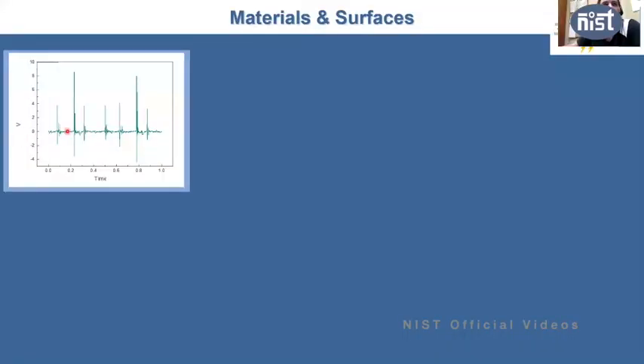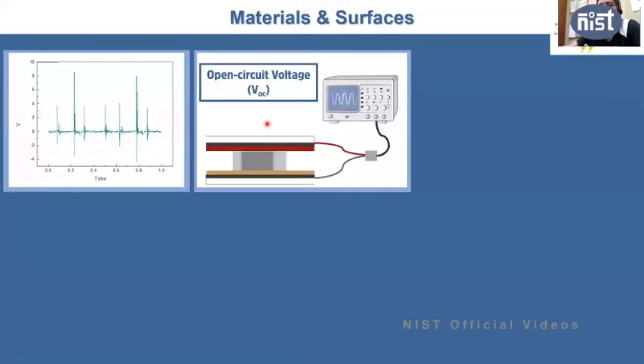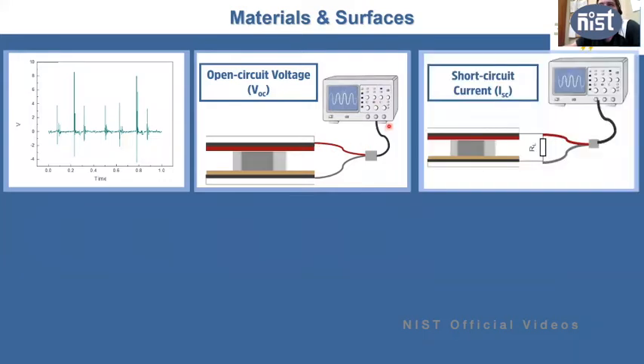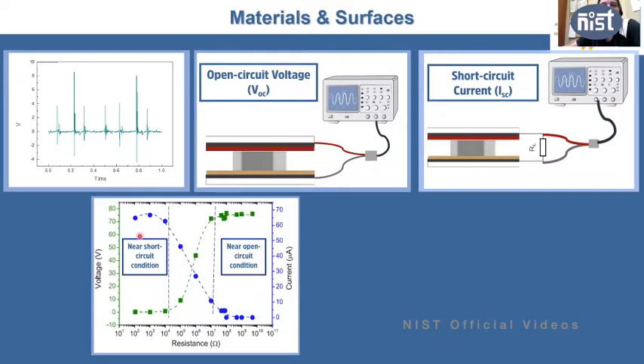And you obtain something like this, so a voltage as a function of time. And you get three basic quantities that you want. The open circuit voltage, so when the two triboelectric electrodes are on open circuit and you measure it directly on an oscilloscope and an ammeter. You have the short circuit current, where you put a shunt resistance between the two electrodes, and you measure the current that comes out of the device. And you then vary this load resistance that you put between the two metallic electrodes.